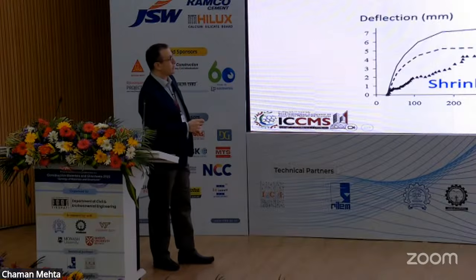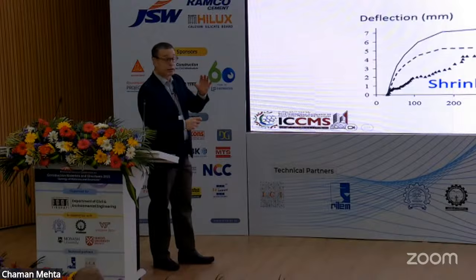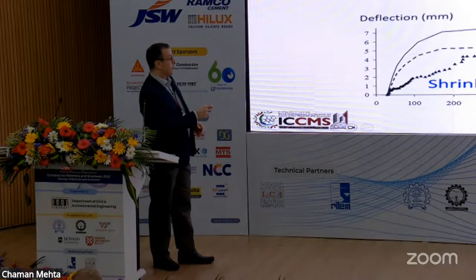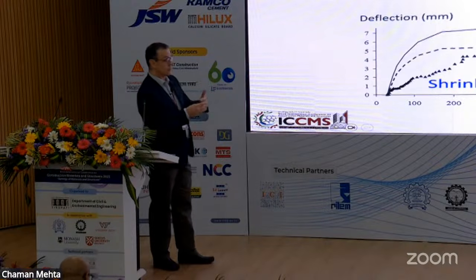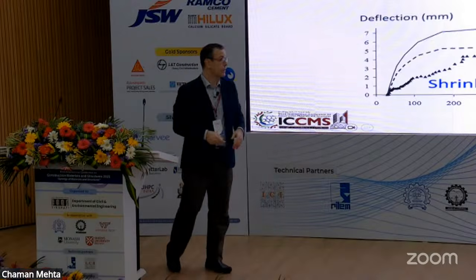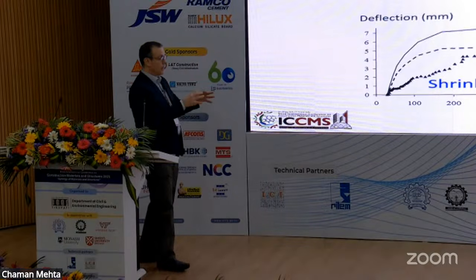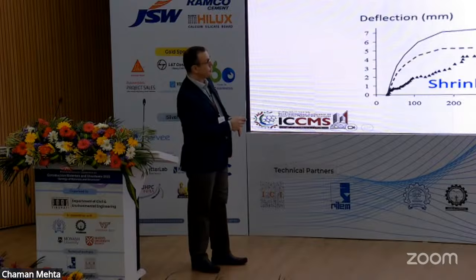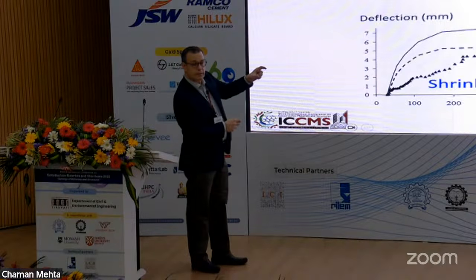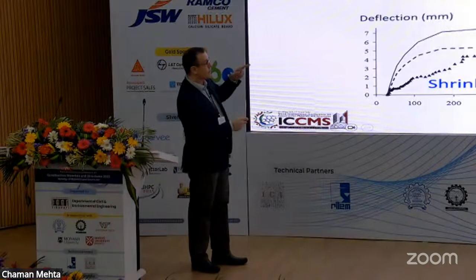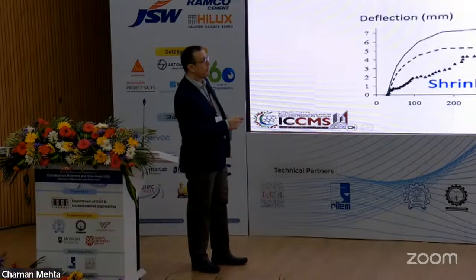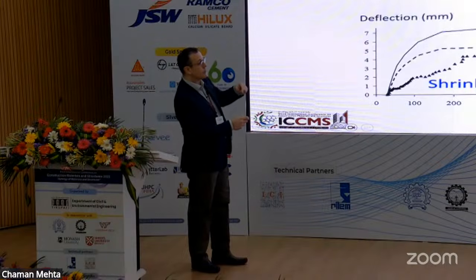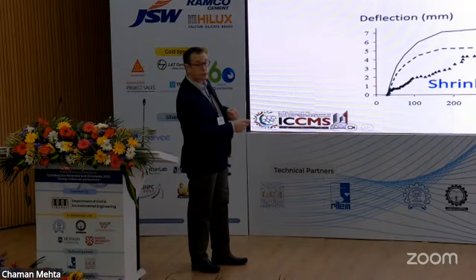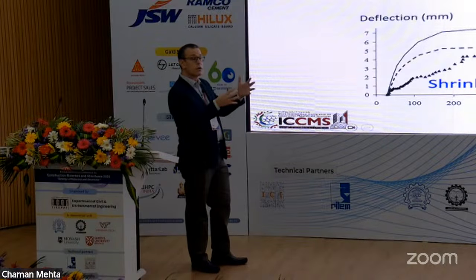What I want to highlight here is that the continuous line assumes a linear elastic shear connection. So it's just a spring, the interface between concrete and steel. And the dashed line is time dependent. So we got a creeping of the shear connection, which has to do with the 3-dimensional behavior of the concrete near the shear connector. And as you can see, shrinkage and creep have opposite effects. So without trying to visualize more with a more refined model, you will never be able to distinguish that creep is overestimating, going above, I would say, the elastic response. And when you look at shrinkage, it's going below. Because usually you look at the results always together.